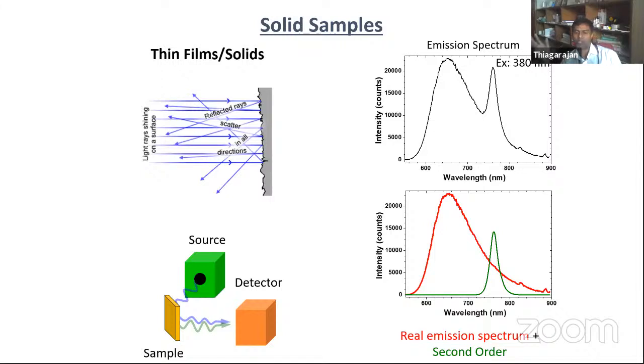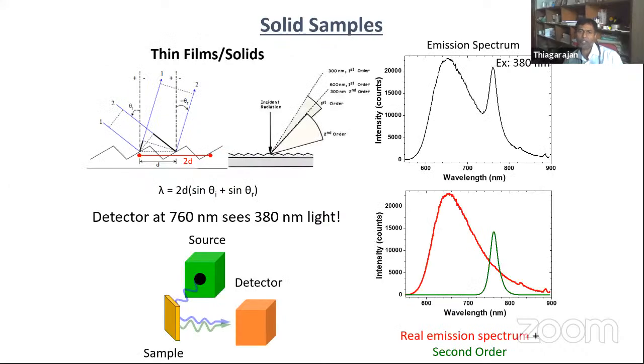When we work with solid samples, they always give a second order spectrum. Second order means, for example, here I am exciting at 380 nanometer. Second order is just multiplying by 2, so 380 times 2 gives 760. You can see the peak at 761 now. It's not due to emission. Some people think that it's emission, but it's from the second order pattern. We can correct it and get the correct emission spectrum. So when we record with a solid sample, we have to be very careful with the excitation wavelength and the second order spectrum.